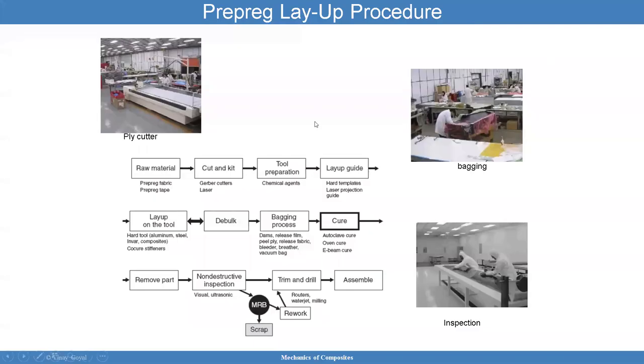So here we have the pre-preg lay-up procedure. We have a ply cutter here, the bagging and the inspection. All that needs to be part of your process. You have the raw materials. We have the pre-preg fabric and the pre-preg tape. And when I say pre-preg tape, what I mean is that the fibers are oriented only one direction. So that could be unidirectionals. Pre-preg fabric is that I have fibers going in two directions, perpendicular to each other.